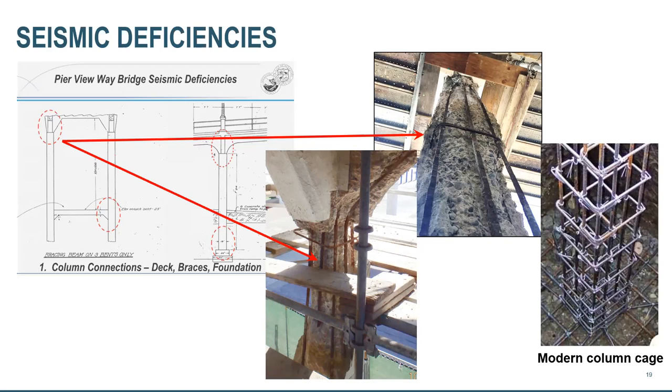But when you guys did the repairs before, I don't think they used that, right? They just used regular bare rebar. I believe they used plain reinforcing steel. David? Yeah, that's correct. They used plain reinforcing steel. They placed what they call anodes in there to try to control some of the salts at the back of the rebar. But in general, most of the rebar that was placed in 1927 is the same rebar as there is today. So the repair efforts were pretty much superficial. Yeah, thank you. Okay, anyone else?